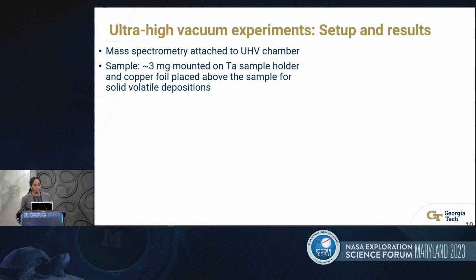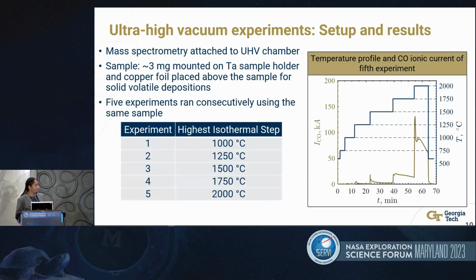So moving on to the ultra-high vacuum experiments, the ultra-high vacuum chamber was equipped with mass spectrometry. About 3 milligrams of sample was placed on a tantalum holder, and a copper foil was placed above the sample to collect volatiles leaving the sample during experiments. So 5 experiments were conducted consecutively, and the same sample was used to study which volatiles were leaving at which